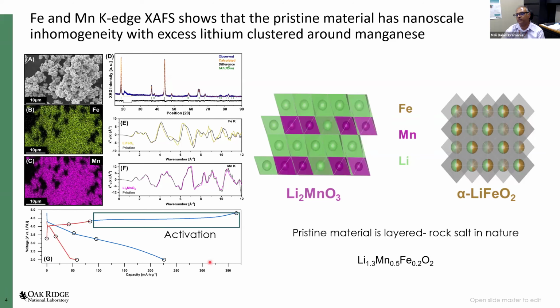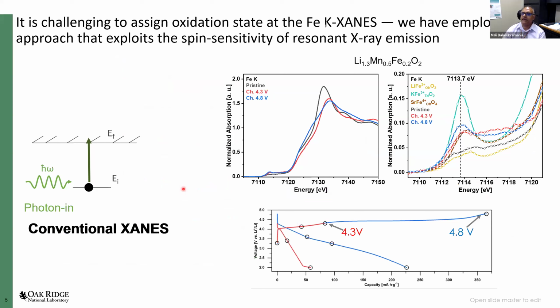This material does not cycle very well, and we are interested in understanding the charge compensation process and the structural changes during electrochemical cycling. We all know that typically X-ray absorption spectroscopy has been used to understand the oxidation state of the material. We are interested in how the oxidation state of manganese and iron evolve during electrochemical cycling. It turns out that in the case of iron, as I have shown over here, a variety of iron 3+ and iron 4+ compounds have a pre-edge which is more or less coincident, and it occurs at the same place.